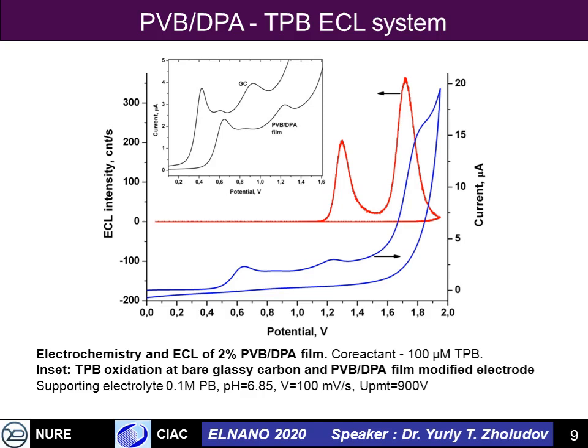After deposition of such a film on the electrode surface, on the glassy carbon disc electrode, the electrode was placed in a conventional three-electrode ECL cell, and cyclic voltammetric potential scans were applied to the electrode. The potential was linearly increasing from 0 to some maximum voltage. Here on this slide it is up to 2 volts, and then reversed back to 0, at a scan rate of 100 millivolts per second.